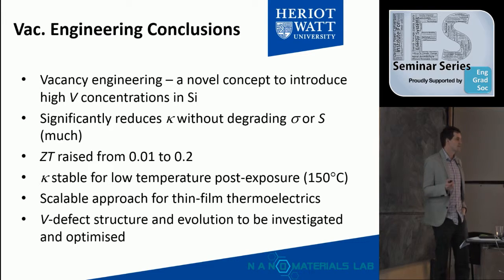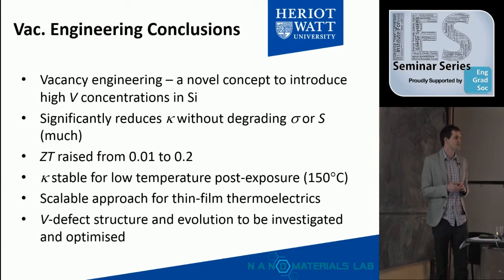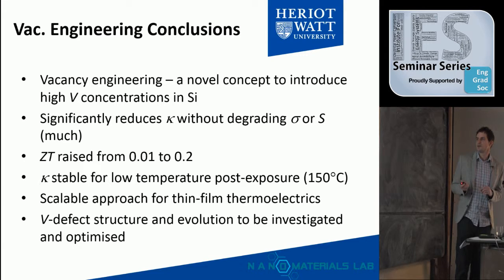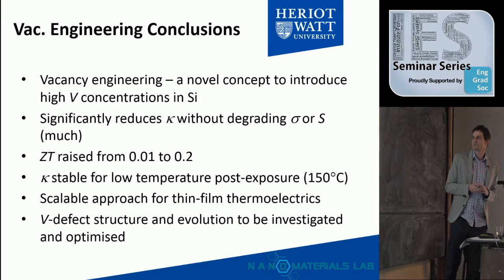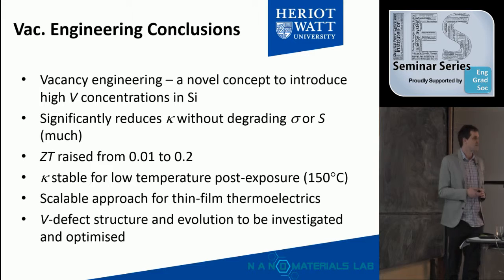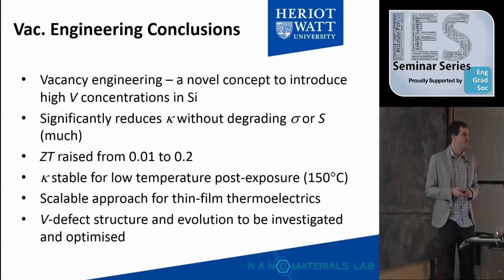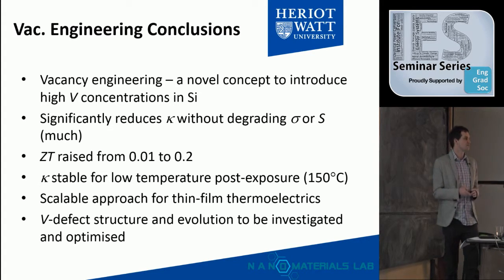So just some conclusions on this section. We think this is a novel concept as a way to try and improve thermoelectric performance in silicon. We can significantly reduce the thermal conductivity, maybe not as much as we'd like, but we've made some good progress. We don't really degrade the other important properties very much, and we've gone up 20 times in our ZT so far. As I've already said, the scalability issues look okay so far in terms of the due diligence we've done, and we're now looking at these thin film structures and devices of that nature.